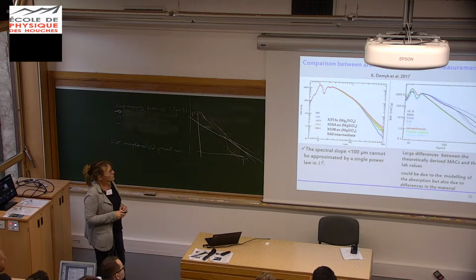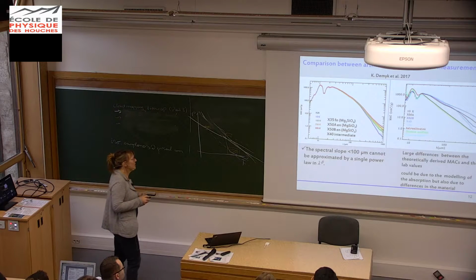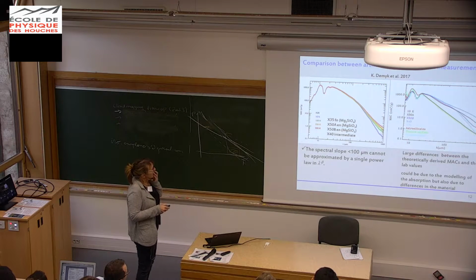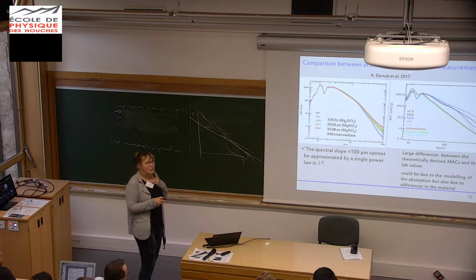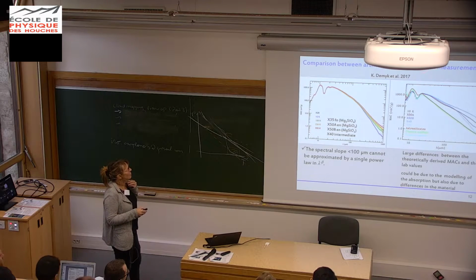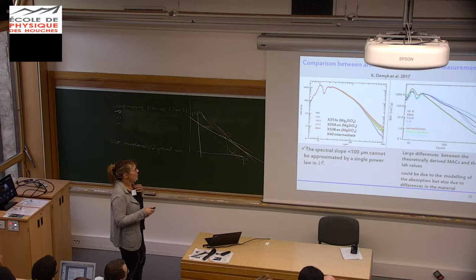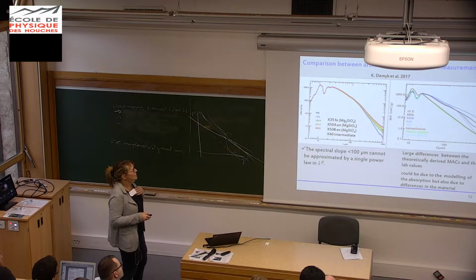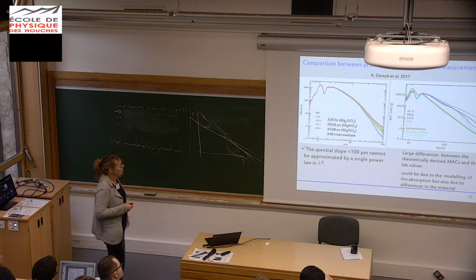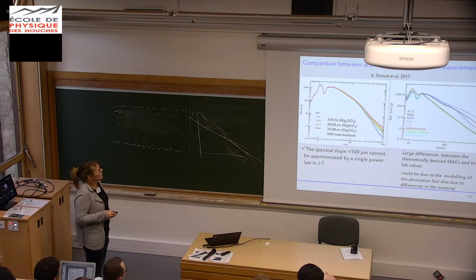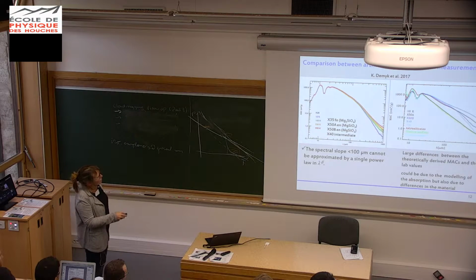Another problem I wanted to show for the moment is that spectral properties are also temperature dependent. This was clearly shown by Demyk et al. This is also very important if you consider, for example, long wavelength spectral properties of silicates or of oxides. The problem is if you decrease the temperature, you get a decrease in the absorption, and also a change in the slope of the curve.